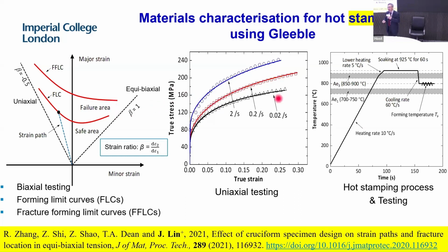But it's very difficult to generate the data because it's a new technology, and until we developed the technologies, nobody in the world could generate data to get the forming limit. And the reason is that in the hot stamping process, as I mentioned, you increase the temperature to a certain level to do the heat treatment for the material. Then you need to drop the temperature to a certain level with a controlled cooling rate. With the controlled cooling rates, then you do tensile testing and get the data. But it's very difficult to control the cooling rate, and this is a problem.